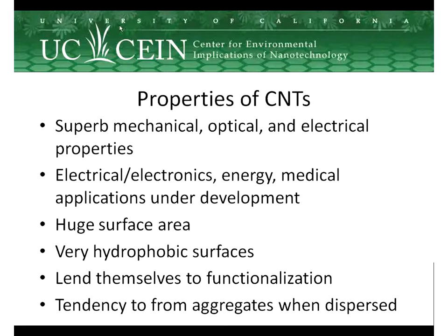What we mean by that is that you could have, for example, carboxyls, which are typical. You may oxidize the surface a little bit so the carbon has a few oxygens present, and that will help it to get into water and disperse well, and also for other interactions they may be interested in. Amines could also be some of the functional groups. But they have this issue that they tend to aggregate when dispersed.